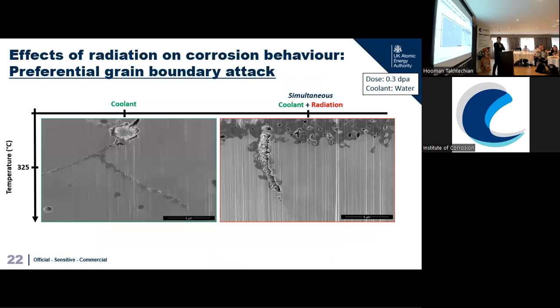This is a higher magnification electron micrograph showing the region where you see preferentially oxidized grain boundary. And in the same material exposed to coolant and radiation, we also have preferentially oxidized grain boundary, but there are differences. The region exposed to just coolant shows dense oxide, which is good, in the sense that a dense oxide makes it harder for oxygen to diffuse into the material.